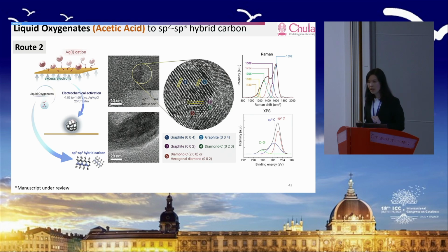And here is another route where we modify the synthesis system, where we don't need to pre-deposit the metal. We just have the copper foil, and we add an ultra small amount of silver in the solution, apply a small amount of electricity as well, and in the end we are able to create the same thing. So the carbon that we obtain is pretty much the same as the previous route.